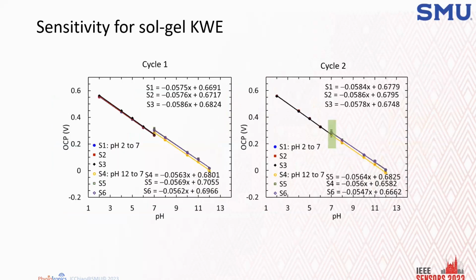Then we take the result and plot the sensitivity curve. We plot it for cycle 1 and cycle 2. In cycle 1, the devices are still being hydrated, so we do expect the performance to be a little bit less than the hydrated one. But we found that the sensitivity in acid and alkaline are pretty much the same. And when they approach from acid or alkaline, the performance at 7 is roughly the same.